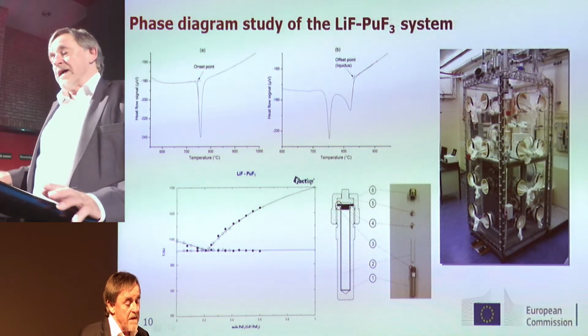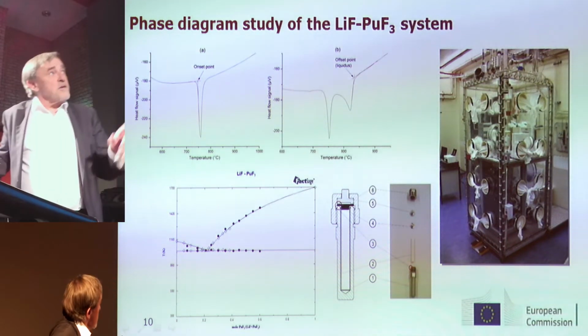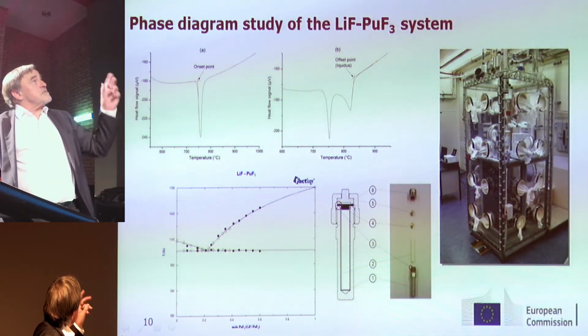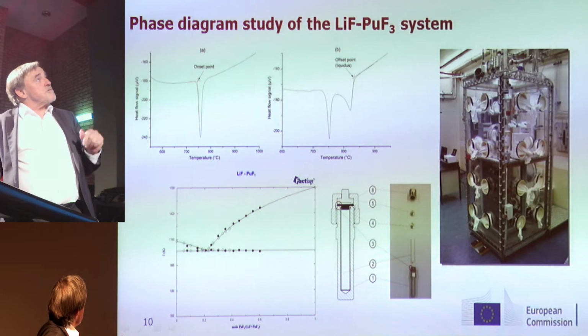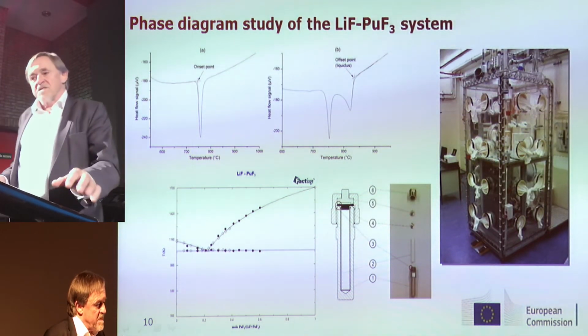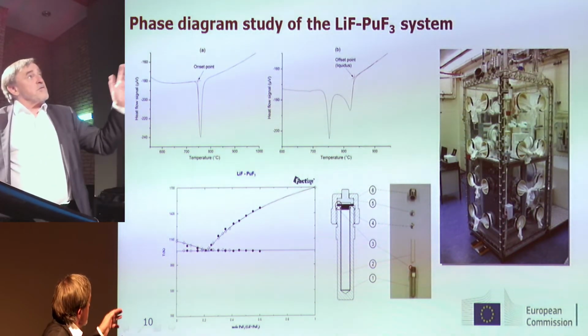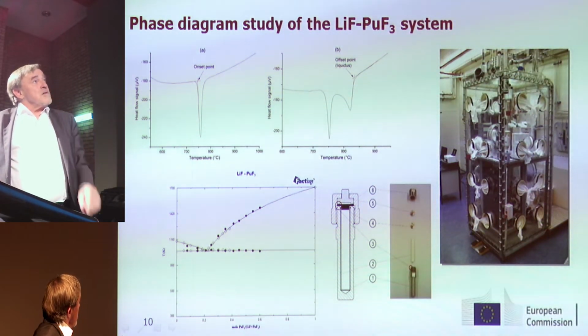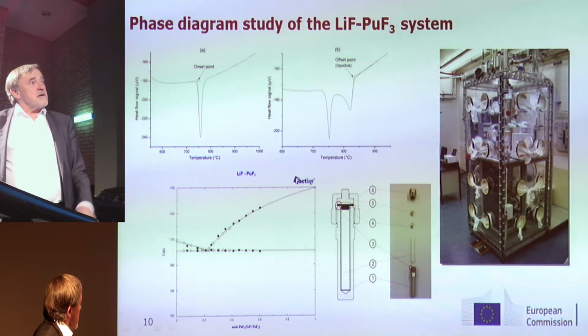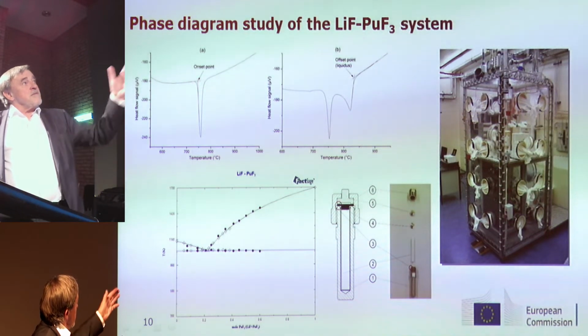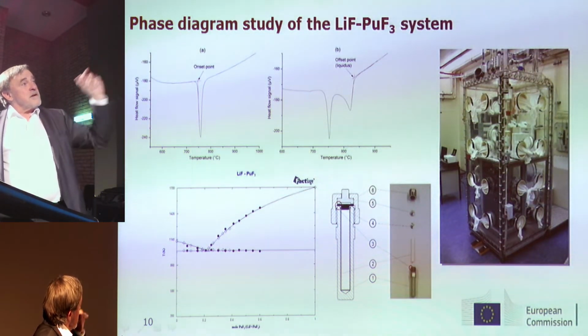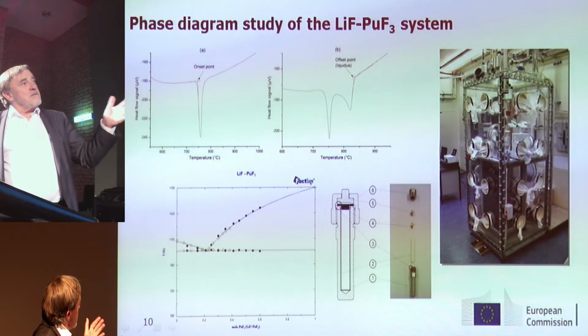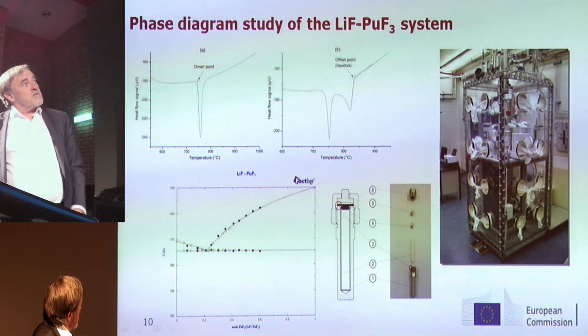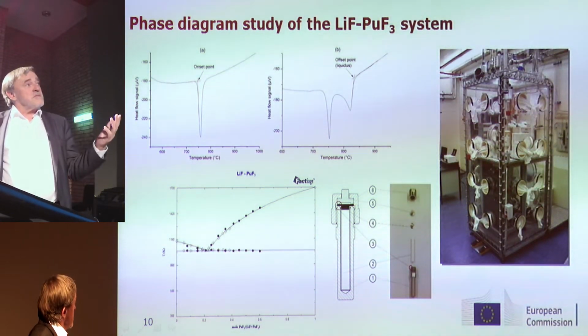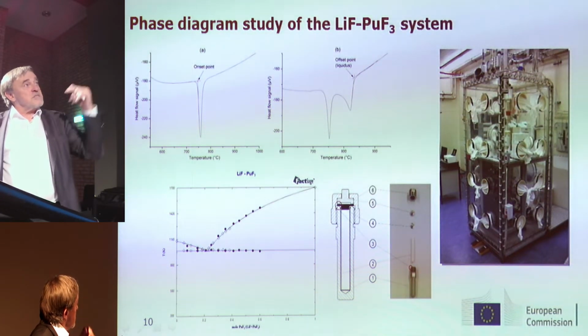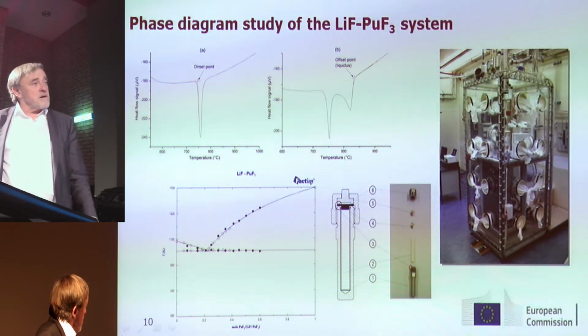So this is the system again, and you see then the data which are being used. So we have these curves which are registered for the melting point. So we have the onset of the melting process, and then also the end, the offset point, where the complete sample is liquid in the container. And then we include this data in the phase diagram, and additionally to the experimental work, we try to verify the validity of this data, or to check this with the FactSage calculation program.